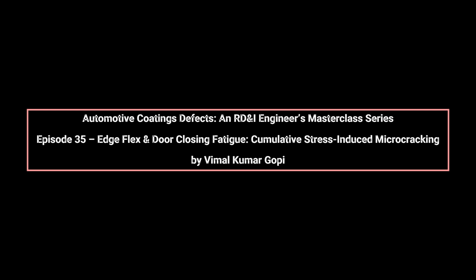Residual stress from curing amplifies fatigue damage. As coatings cure and shrink, tensile stress is locked into the film, particularly at edges and fold lines. Each door cycle adds dynamic stress on top of this static preload. Over time, the combined stress exceeds the fatigue endurance limit of the polymer network, even if the coating appeared defect-free at delivery. Additives influence fatigue performance indirectly.